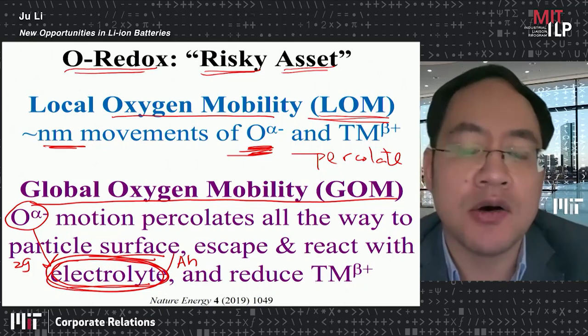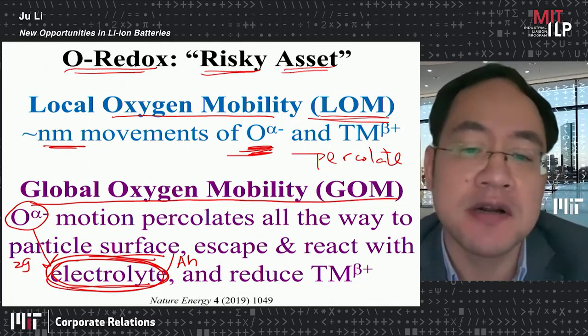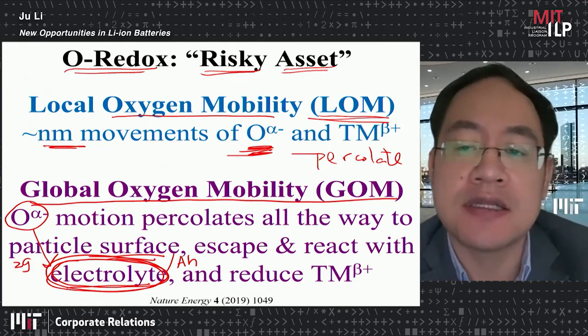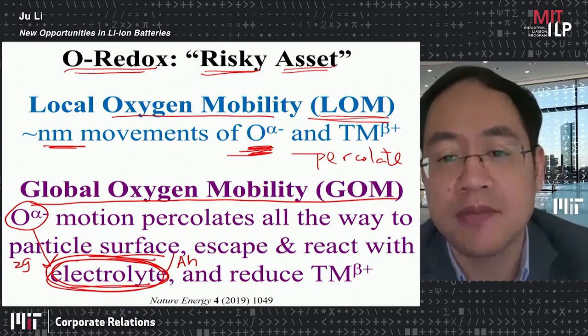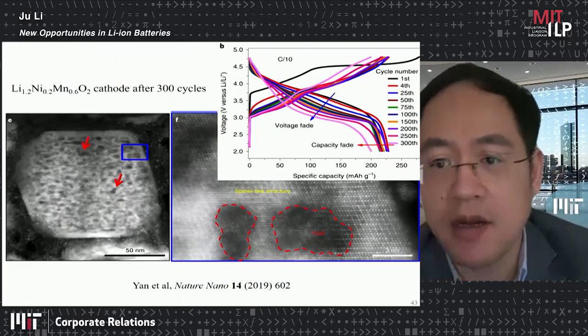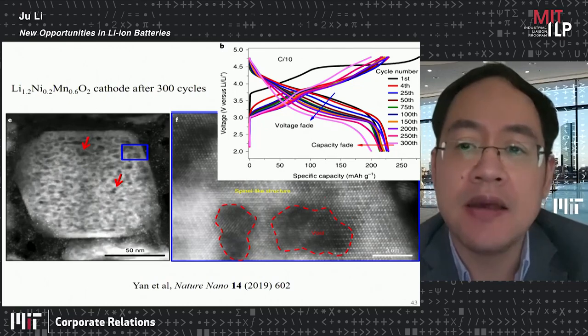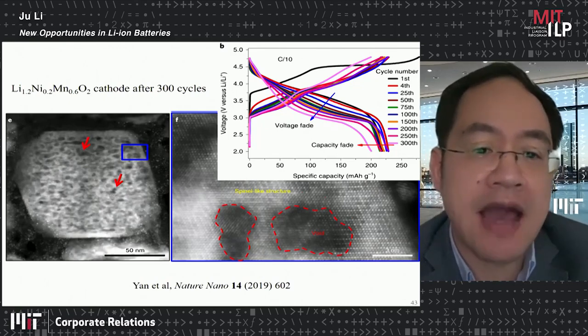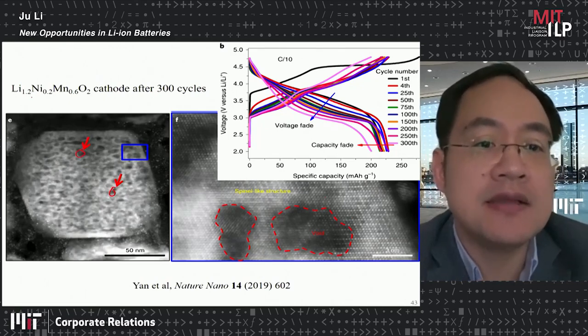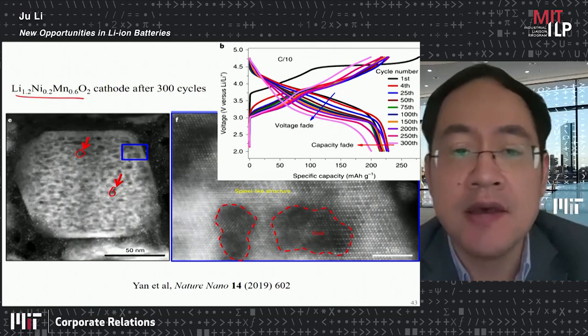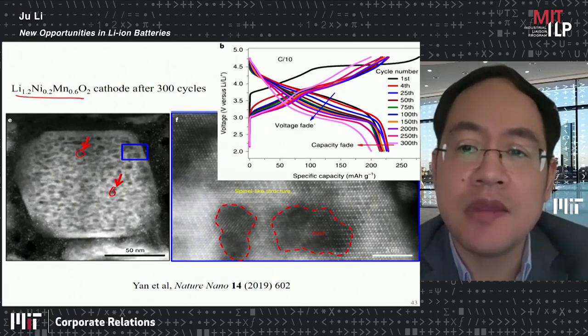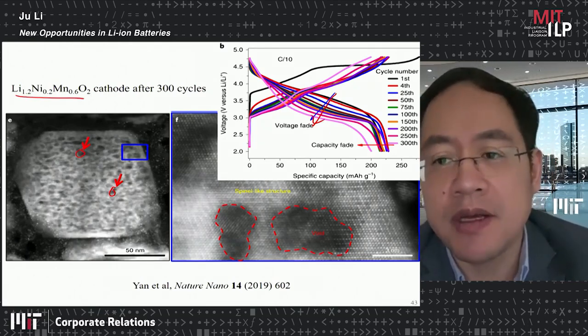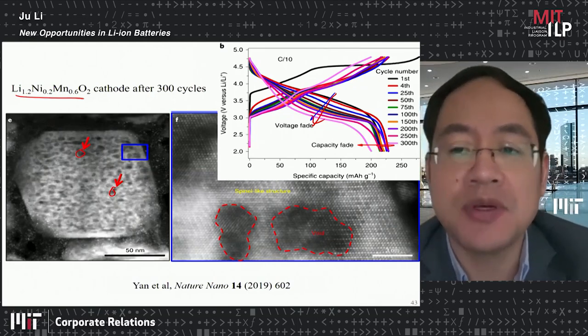mobility, and you have a collapse of your layered structure from the surface, and this collapse is not a self-passivating process. So for example, there is recent work that shows that you have all these cavities that develop in these over-lithiated oxides, and associated with that, it's this voltage drop and reaction with the electrolyte.